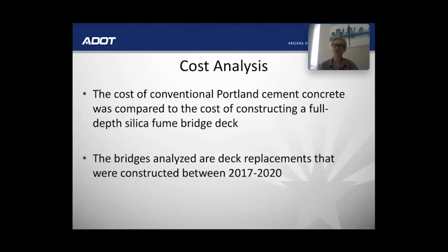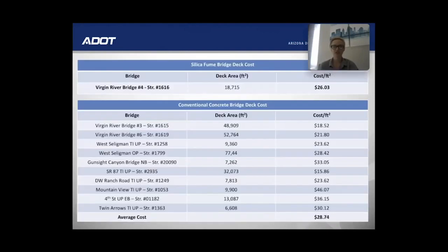So these tables give the individual and average costs of the two different deck systems. And as we can see here, the cost of the full depth silica fume deck is about 10% lower than the combined average cost of the structural slabs with normal Portland cement concrete. It was actually expected that the silica fume concrete would be slightly higher in cost due to the typically higher cost of silica fume compared to cement, also the limited number of full depth silica fume decks that have been placed in the state of Arizona, and also the need to adapt various construction procedures for its placement.